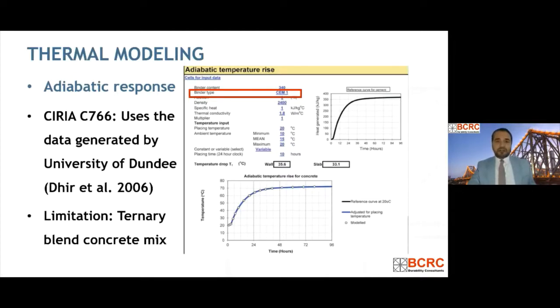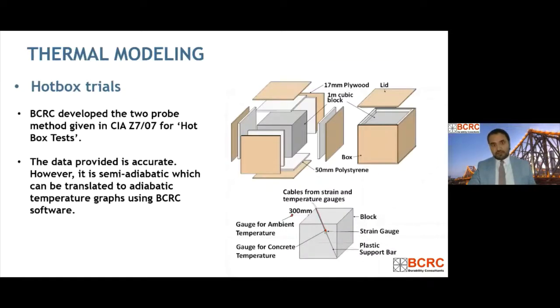But if you have a ternary blend where you have fly ash and slag together, you cannot use this spreadsheet unless you are very experienced and you know how to handle the situation, and you have seen the adiabatic response of these mixes before. Like you cannot straight away use this spreadsheet, right? So this is the main limitation. So that's why the more accurate way to get the adiabatic response of a concrete mix is to perform a hot box trial, right? So at BCRC we developed a two-probe method, which is given in CIA Z7/07.